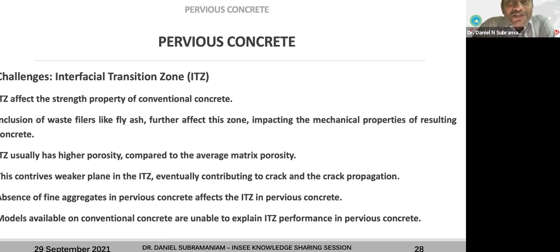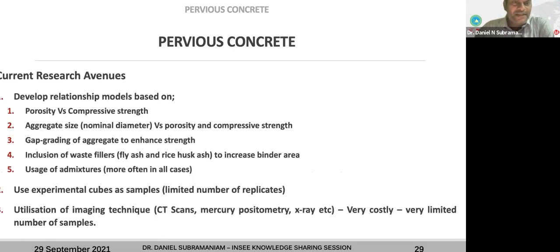So it actually alters the ITZ. So the thickness of the ITZ, how much it is contributing to the mechanical properties, because they also found that most of the time the crack is propagating through the ITZ. So our application should be focusing more on enhancing the ITZ than on what we have in the matrix, as in the rest of the binder, right?